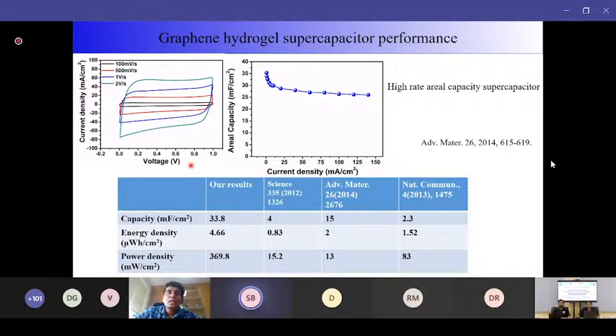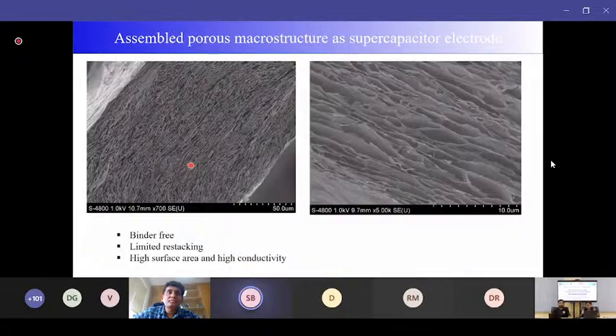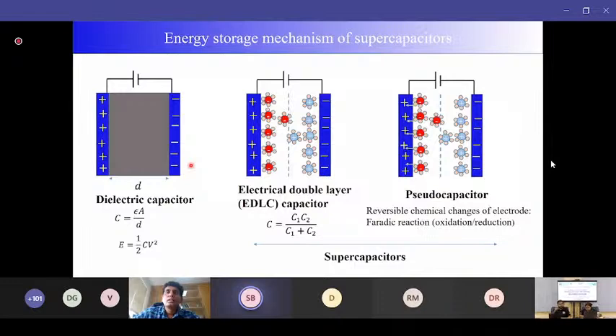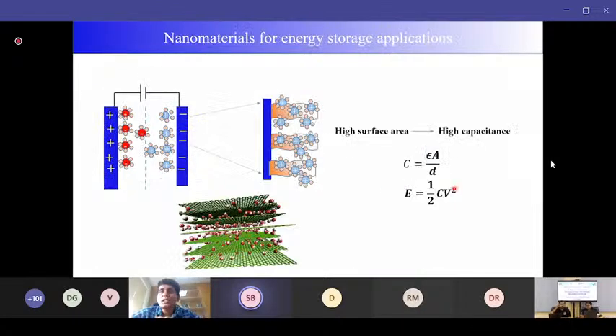So the ionic movement within those viscous electrolytes is less. Although you can increase with those, you see that energy E is equal to half CV square. So although you can increase the V, because the potential is squared, if you can increase the potential window, it is always better to get the higher energy density. But at the same time, because of the high viscosity, the diffusion of the ions will be less. So as a result, the capacitance decreases to a great extent.